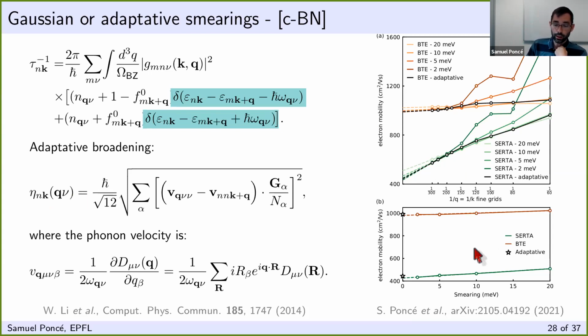And here I'm showing the result for cubic boron nitride again. This is the electron mobility, and I'm showing the result for the iterative solution and the SERTA for different smearing values. So this is fixed Gaussian smearing, and you can see that I'm basically having those values. I can extrapolate to infinity, and I'm getting the value at infinity. And I'm also showing the value for the adaptive broadening, again extrapolated to infinity.